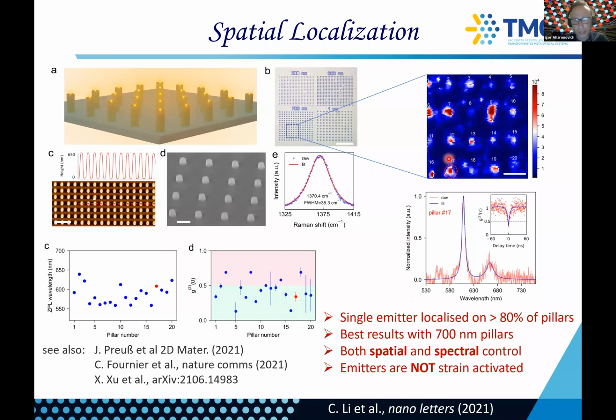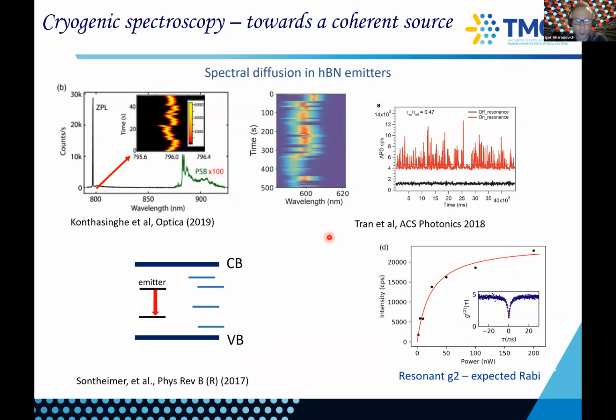And so now you can really take the system and perform a little bit more detailed optical characterization to see how we are going towards a coherent source. And so here the results are really not so great, or I should say poor. So we can see very narrow ZPLs, of course, but unfortunately, as you scan the laser, there is a lot of spectral diffusion. And so even though you can excite them resonantly, when you tune your laser directly with your emitter, you don't see any Rabi oscillations. You would expect here in this g2 function to see Rabi oscillations, as I'm showing you here with my laser pointer, because this is a resonant excitation.